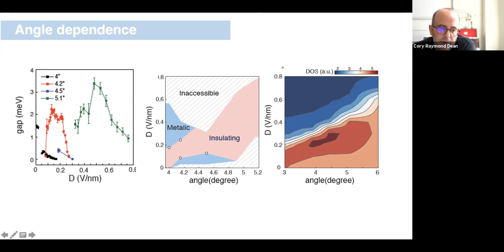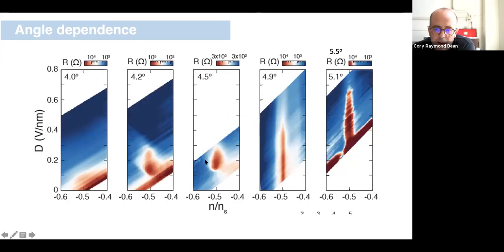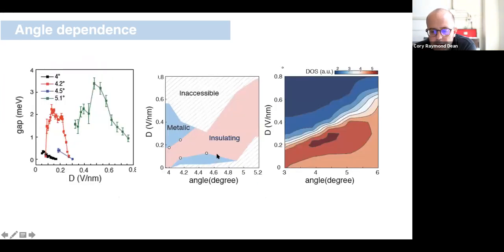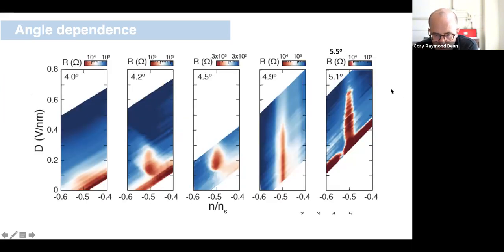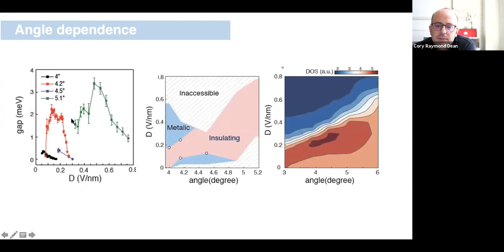So here I'm showing a plot of extracted gap. So this is the gap across this insulator. As I vary D across this insulator, we measure the gap. We plot that here for the different twist angle devices. And we see that the gap spans different ranges. That's exactly consistent with what we see in this data. And we also see here more quantitatively that the magnitude of the gap varies depending on which twist angle we're at. So at 5.1 degrees, we see the strongest gap that we observe in any of our devices, and that diminishes as we go to smaller twist angle.